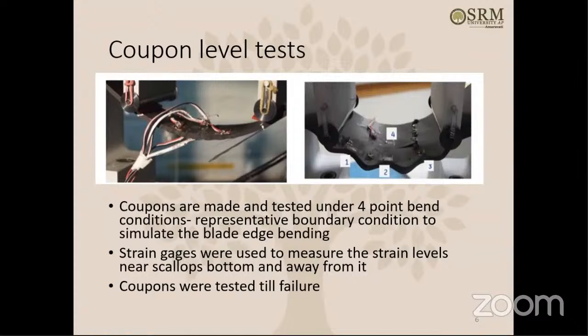We put strain gauges exactly at the bottom point of this wavy shape. There's one strain gauge here, another here, another here, and then one strain gauge far away from the wavy feature. Similar strain gauges were put on both coupons, and we ran the test. Strain gauges were used to measure the strain level.